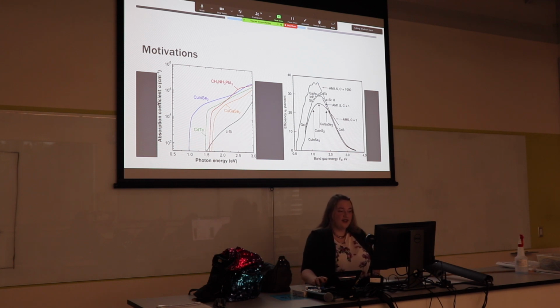Copper indium diselenide here is a clear winner for how broad it can reach for the amount of wavelengths that it can absorb. And it's also a clear winner for the absorption coefficient. So that's why we chose that. Also in this second graph here, we have our band gap energies. We can see copper indium diselenide way up here in about the 22% efficiency range.